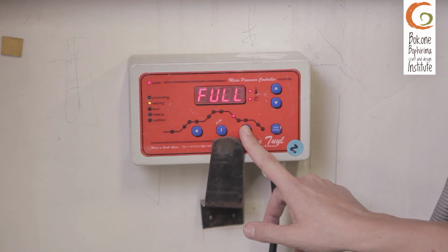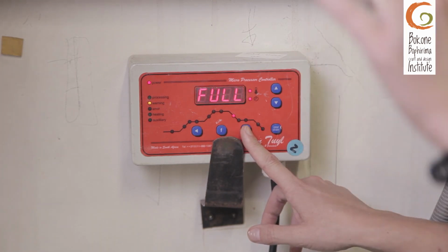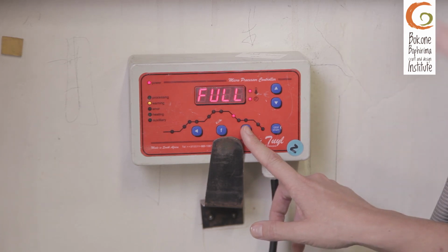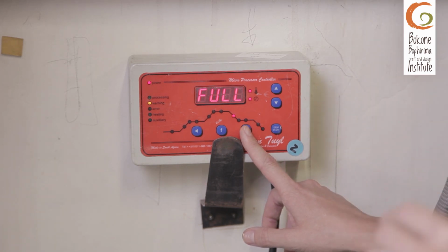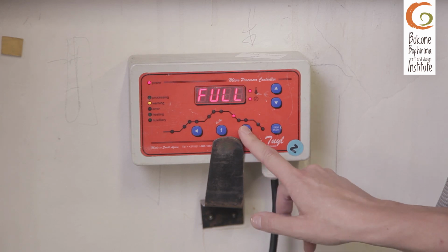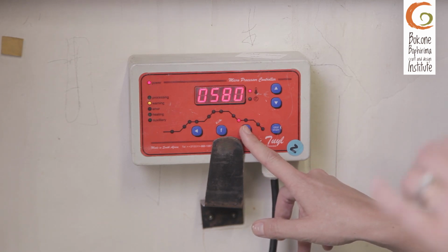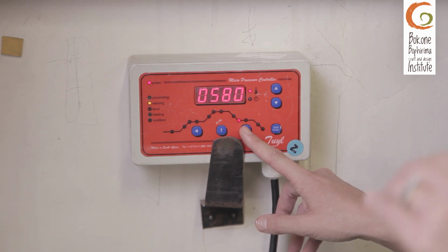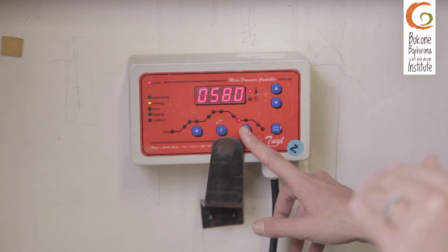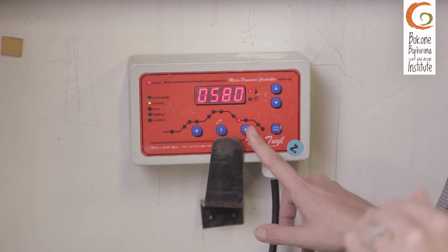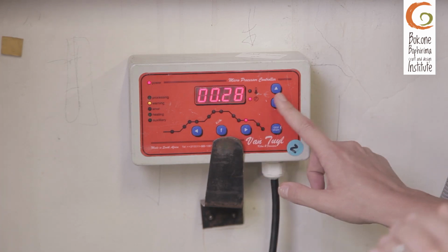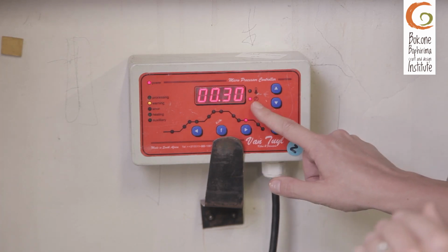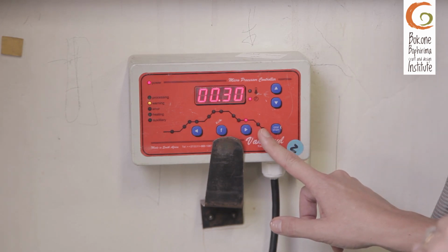We are then going to crash cool. So we want it to go as fast as possible down, because we are not manually doing this. We're allowing the kiln to do this process for us, down to 580. Again, this is where our glass starts to become fragile, and we want to make sure that our glass goes down slowly from this temperature. But first we need to make sure that our glass is all the same temperature before annealing it down.